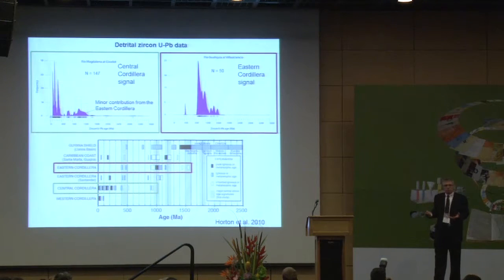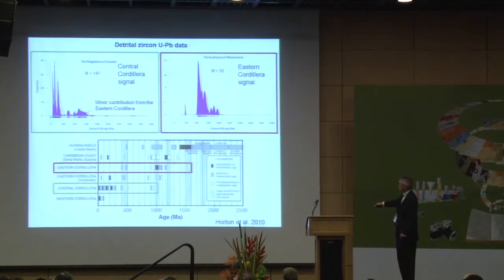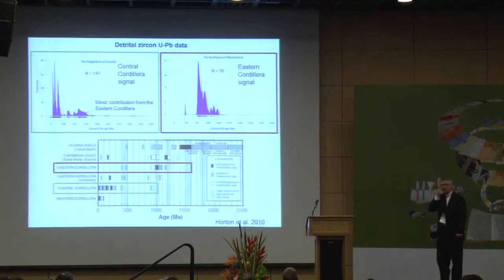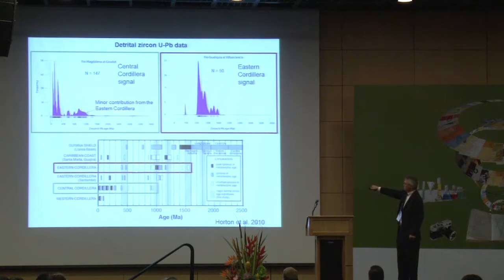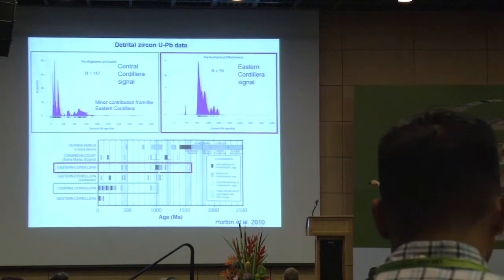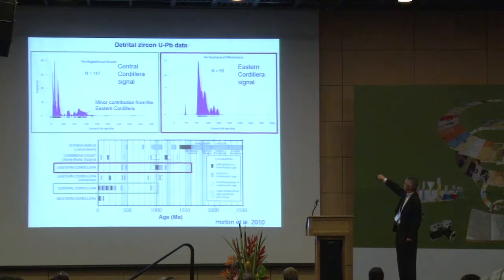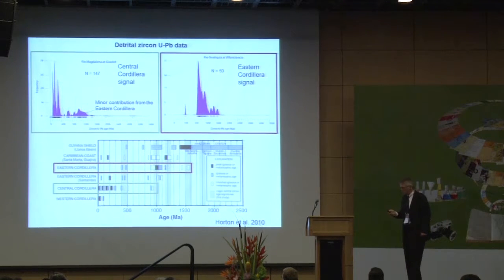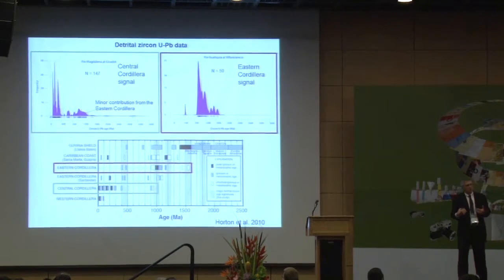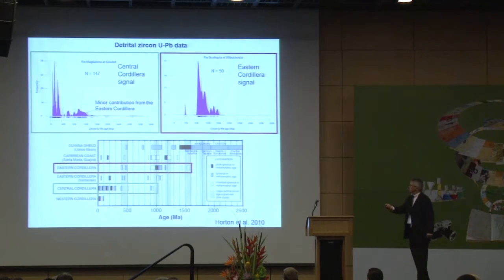But if we compare our results to check how good our data are, we can compare this to the work of Brian Horton, who's going to talk to us, I think, on Thursday. We get basically the same signal. This was the signal that they published in 2010 about the Eastern Cordillera. The ages between 400 to 500 million years, then a big peak at 1,000 million years, and at 1,500, 1,600. This is the same that we see here as well. Only 50 grains, so we only get a couple of grains here, but it's definitely the same spots. And the signal from the Rio Magdalena is the same spectrum that he found, except that we have this little bit of a tail, maybe a little contribution a bit older that may come from the Eastern Cordillera. But in general, this works. Our results are the same as those produced in other labs around the world, and this is, of course, good confirmation.